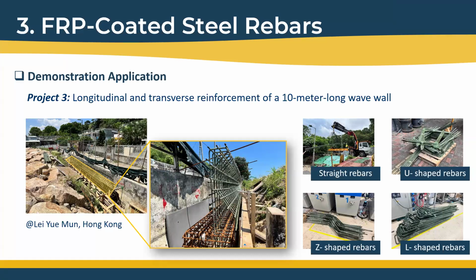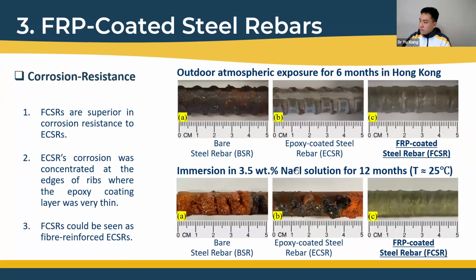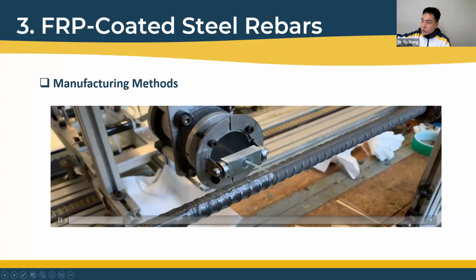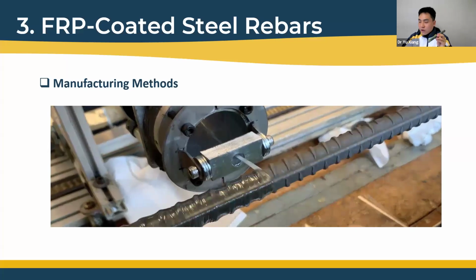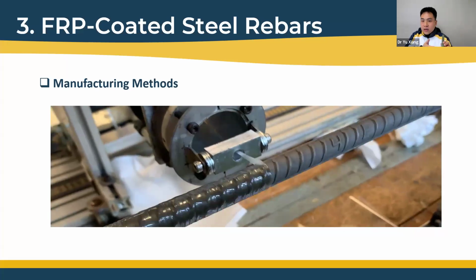The final question: is the FRP coating technology also applicable to steel H or I sections? Some of my group members are trying to apply the FRP coating technology to other shapes of steel profiles, like H shape or I shape. But the problem is with the shape—if we want to do filament winding and there is an inward shape in the profile, it will be very hard to make the coating layer properly fit the shape of the profile. So my answer is yes, applicable, but there is difficulty in achieving the same effect of the FRP coating.